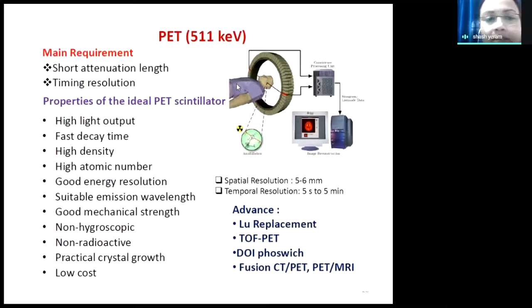The scintillator material in this case cannot be cesium iodide. One reason is that cesium iodide has afterglow. For PET we have to detect 2 gamma photons simultaneously, because then the precise location and working can be found out. Cesium iodide is a slow scintillator material, so it cannot be used. We have to find a better, faster scintillator material.